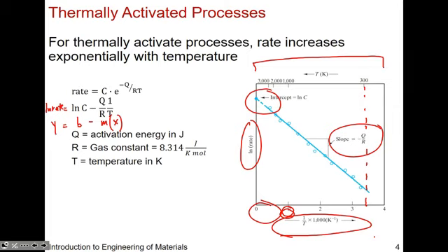So what typically happens is people don't actually plot this area, they just end right there. You plot it to some high T where the diffusion mechanism is the same, and then you just stop. You just don't measure anymore, because the closer you get to the melting point, the more differently your atom behaves, and it doesn't capture the real physics of the system. So it becomes non-physical. Then you're talking about a different regime.